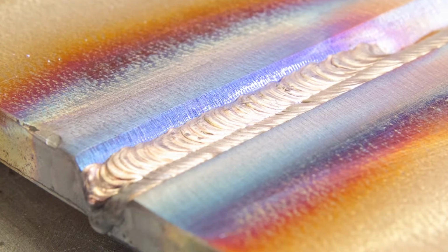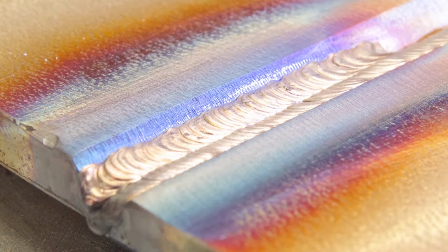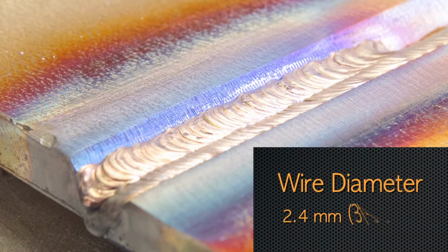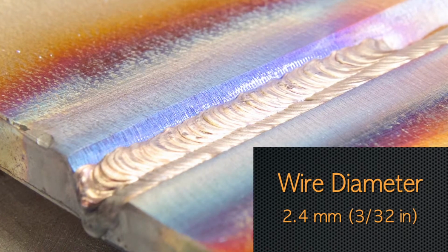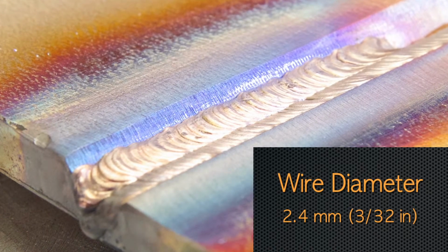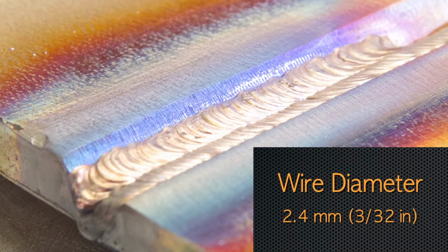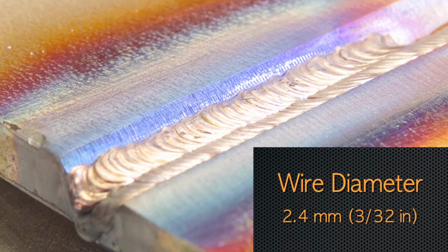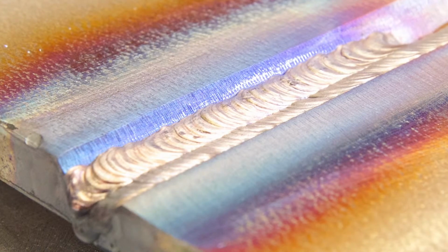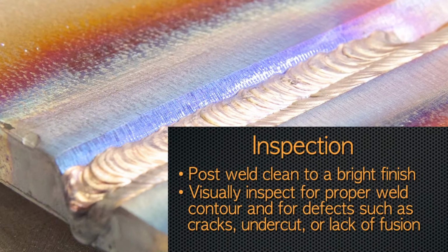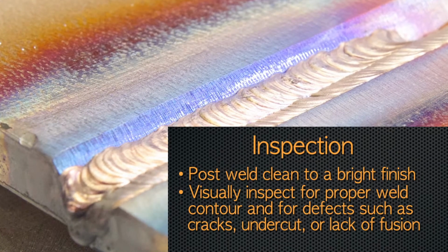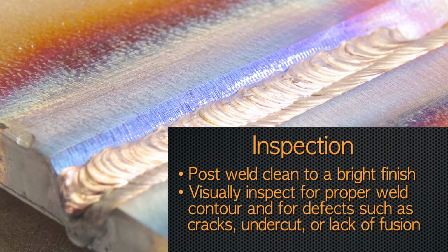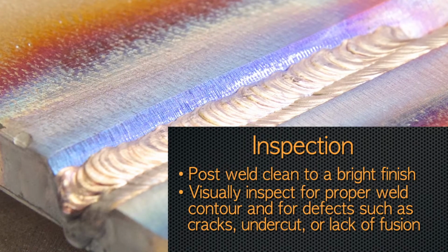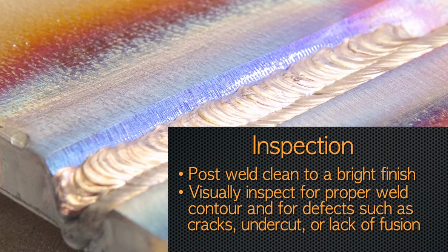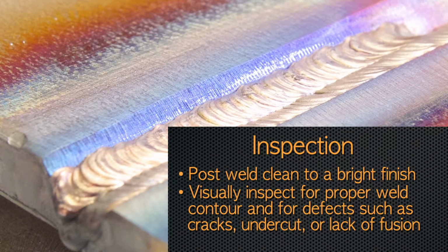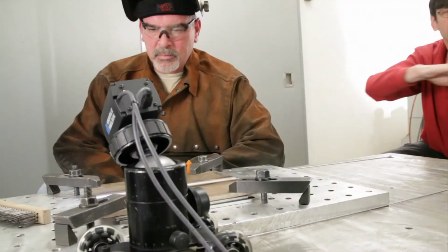We've completed our second pass. We're ready now to start the third pass of this weld. Note that we're using 3/32 diameter filler metal. Obviously larger sizes could be used to make bigger welds. There's no limit on the number of passes. We don't worry about heat affected zones with this material. All we need to do is to make sure that that second pass is well fused with no overlap, no cracks and no porosity. And if there are imperfections in that second pass, we need to grind them out and repair them before we start the third pass.